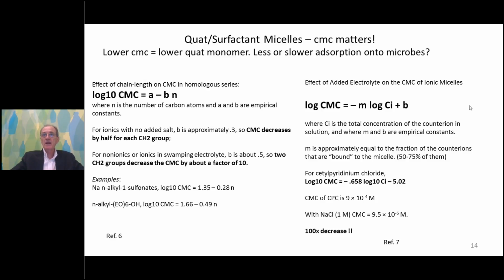And there are a couple of basic concepts that relate to mixed CMC. When we're selecting our co-surfactant, the equation on the left reminds us that as we change the tail length, as we add 1 or 2 methylene groups to the length of our co-surfactant, the CMC can decrease by a factor of 3 to 10, depending on the actual surfactant we're talking about, but it's a significant effect. So small changes in the tail, of course, make a huge difference in CMC.